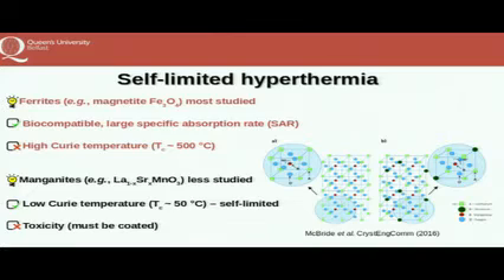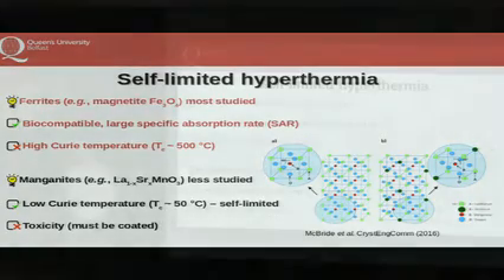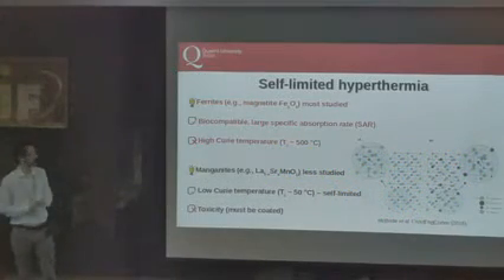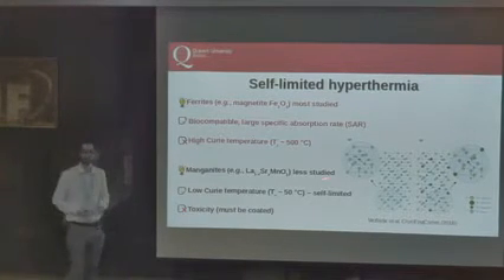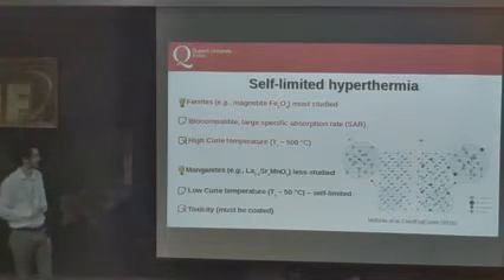That the Curie temperature is much lower. In fact, it has been reported in some compounds to be 50 degrees Celsius. This is much better. So we can really have a self-limited hyperthermia using, ideally, these magnetic nanoparticles. There are drawbacks, of course.